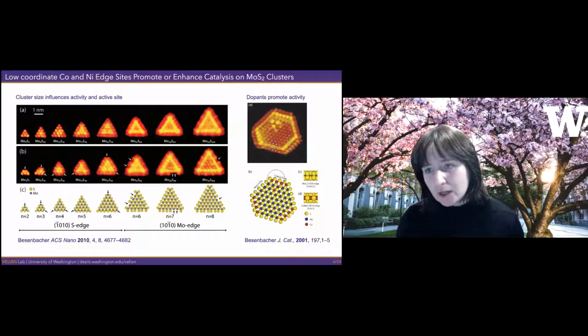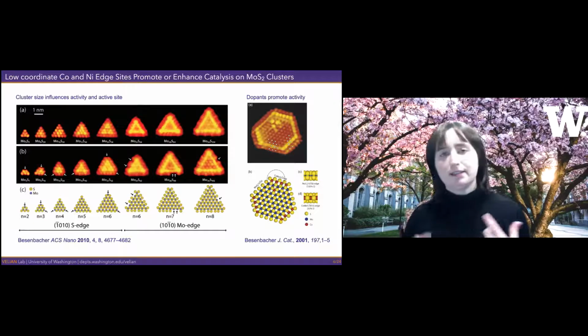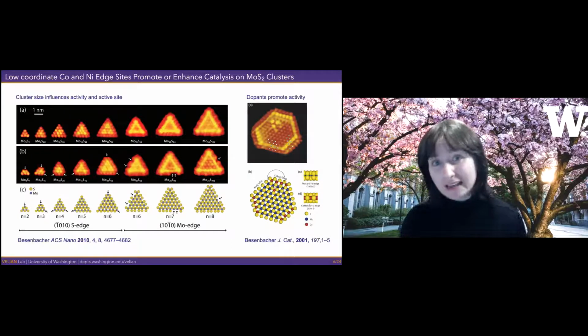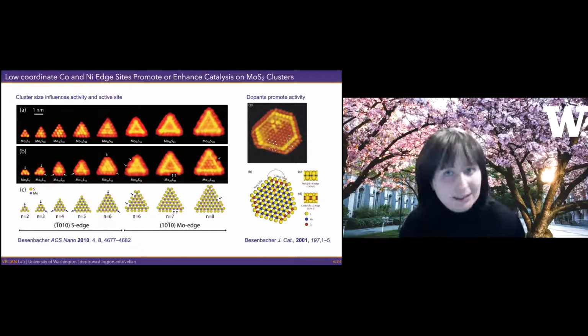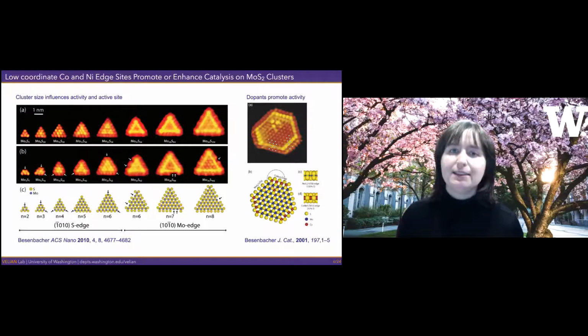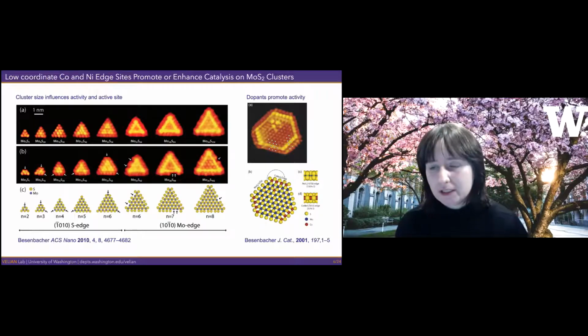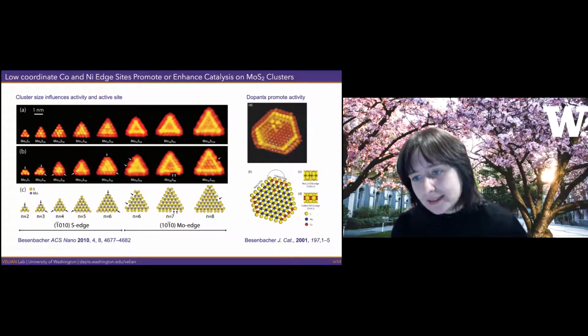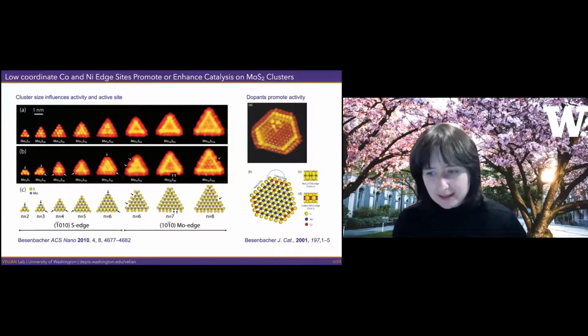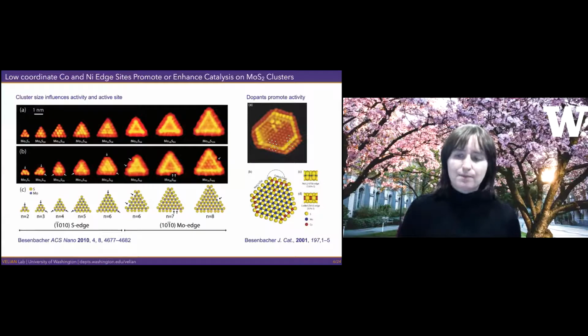And on the right side here, what I'm showing is a separate study in which the authors asked the question of, okay, if you put that cobalt and nickel on this molybdenum sulfide flake, where does it go? Because perhaps we can identify where the active sites are in this mixed material. And it turns out that the cobalt in this case, and same thing with nickel, is really localized on the edges. So it doesn't really insert itself in the base of the flake, although there are some cobalt atoms going in there, but most of them are on the sides. And so we really love this study because it's very hard in heterogeneous materials to get that kind of precision in understanding what happens.